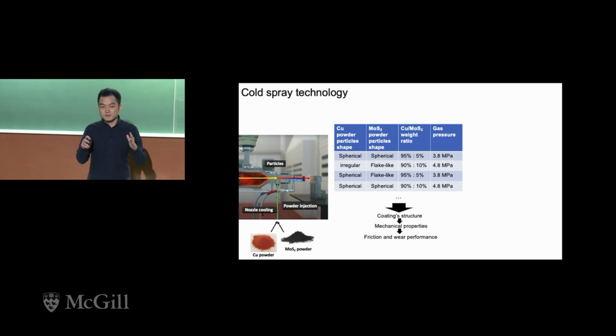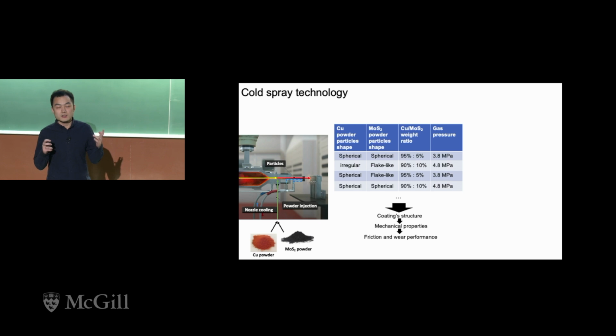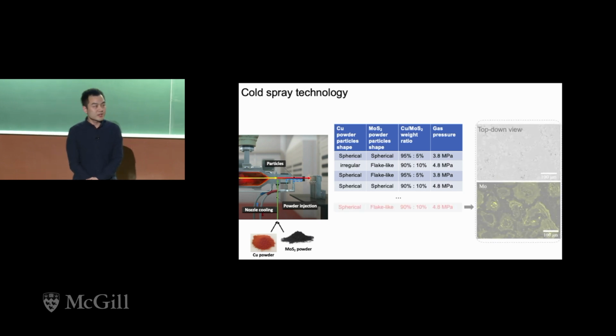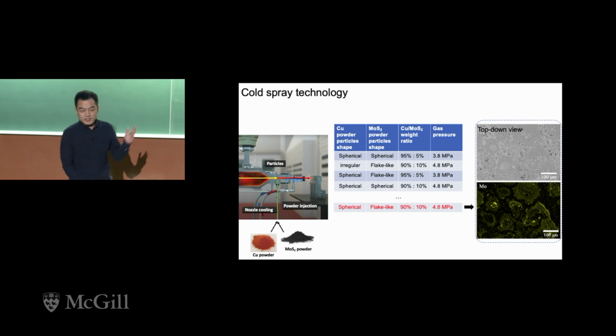After knowing the relations between those three aspects, based on cold spray theories and experiments, we can design the coating we want. After trying many times, finally we got this coating with enough thickness, 30 to 40 volume percentage of MoS2 content, and uniform distribution of MoS2.